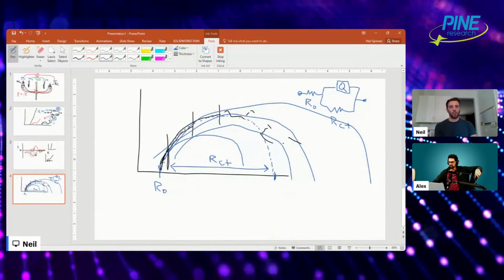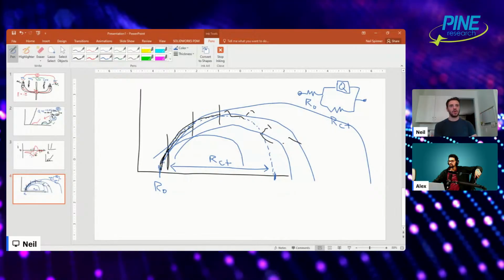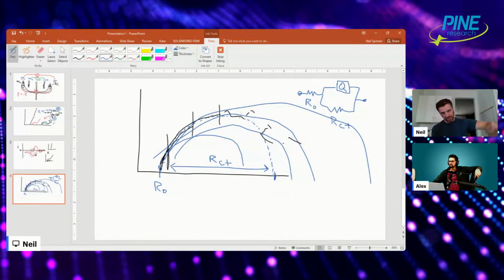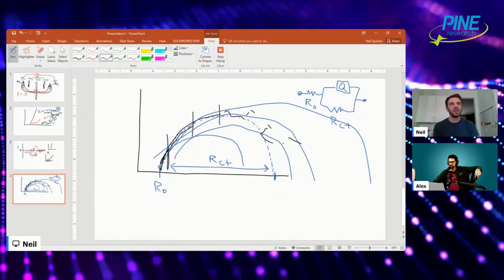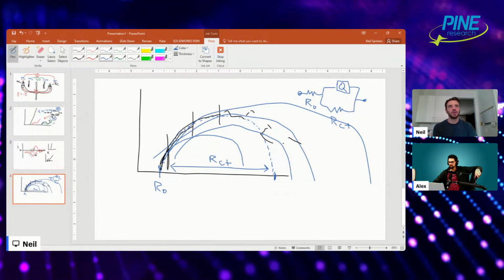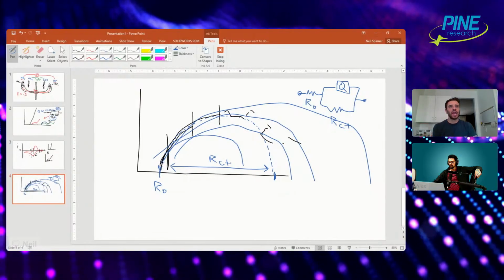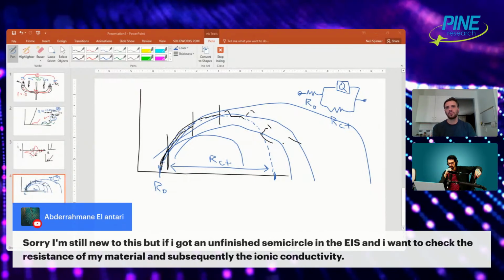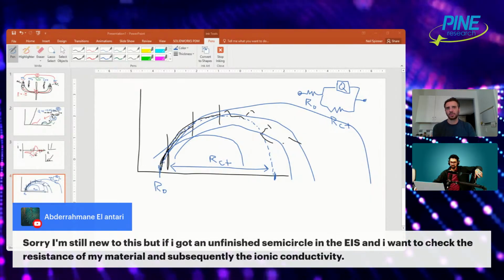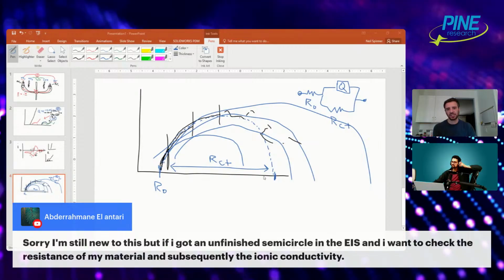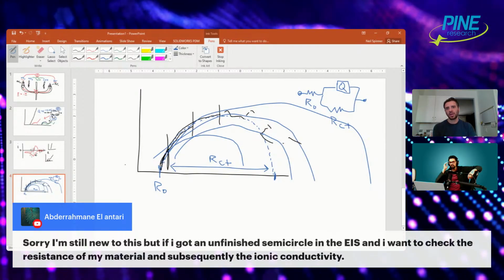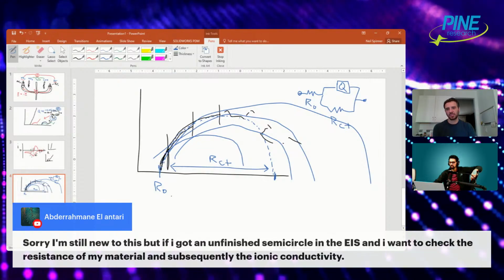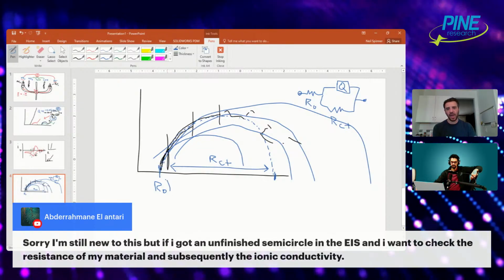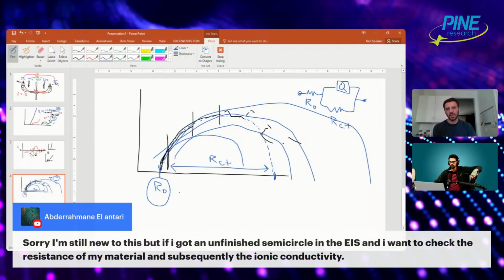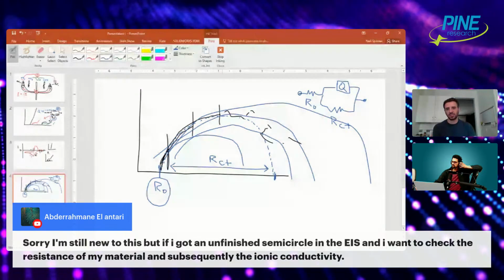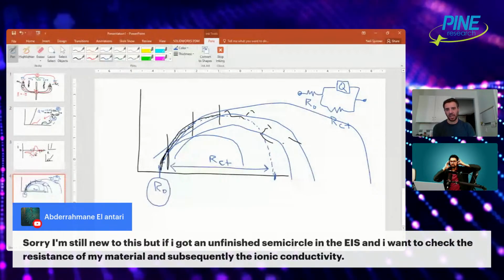And so the more of your semicircle that's there, the better. But there's no requirement that your data has to fully touch the x-axis on the right, on the low frequency side, to be able to obtain fitted values, for sure. And just to be clear, your question was in regards to the resistance of your material and the subsequent ionic conductivity. So the charge transfer resistance is this width, but the ionic conductivity, as we sort of discussed earlier with membrane conductivity, that should probably come from this. The RCT is related to the charge transfer of a Faradaic process.